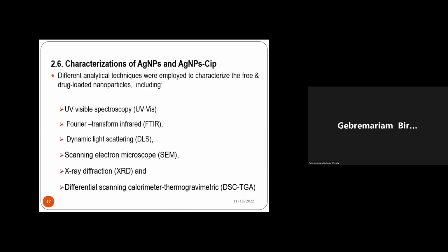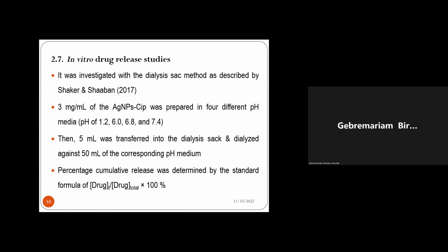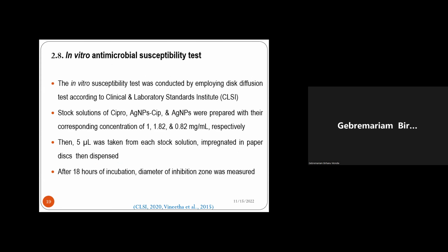Then we characterized both free silver nanoparticles and the drug-loaded silver nanoparticles using different instrumental methods, like UV spectrophotometer, X-ray diffraction, and differential scanning calorimetry. And then the in vitro drug release study was conducted at various pHs using a method adopted from Shaker and Shaaban with little modification. And finally, the in vitro antimicrobial efficacy testing was conducted using the diffusion method, comparing pure ciprofloxacin, pure silver nanoparticles, and silver ciprofloxacin loaded nanoparticles.